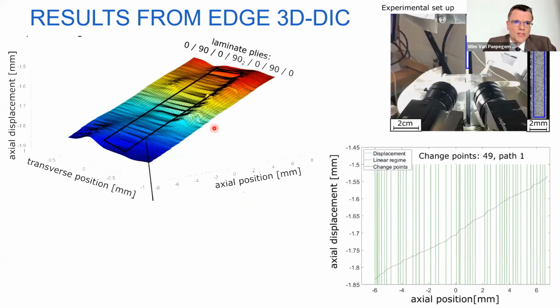If you now go to the edge DIC, we can do even more extraction of data. So here you see the images from the edge taken, and we show here the actual displacement. And you see there are a lot of jumps or discontinuities, and every one of these discontinuities is a crack. Because when you have a crack, which is then oriented like this in the 90-degree ply, that means that the displacement field is not continuous across the crack faces, and you get a jump there.